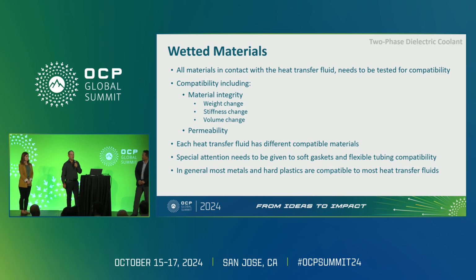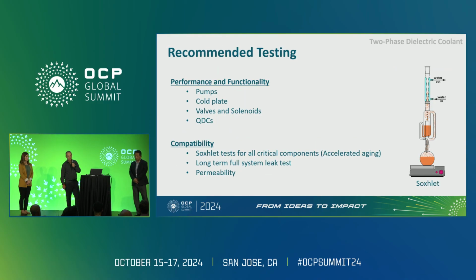And then another test is permeability. It could be that the sealing and everything looks like nothing has changed, but you'll be losing liquid if you use the wrong materials for the sealings of the system. So every liquid has different compatibility with different materials, but special attention should go to the gaskets, the flexible parts, and components like tubing. In general, most metals and hard plastics don't have material compatibility issues, and it's not like PG or water. You do not have to check aluminum, copper, any of them, and they can work together without any problem because of the dielectric features, so you don't have any erosion between components.